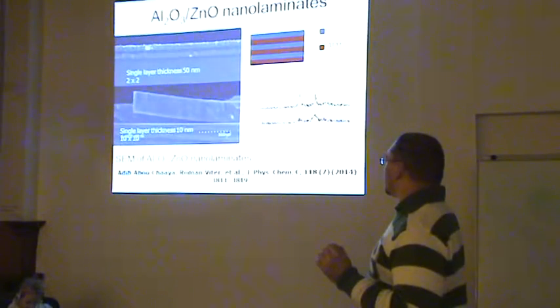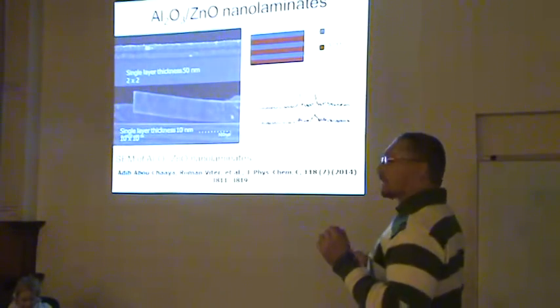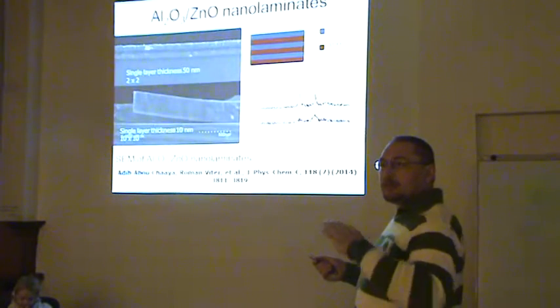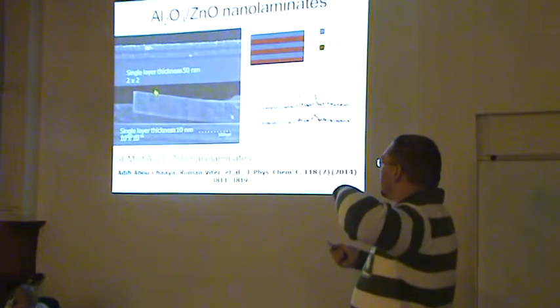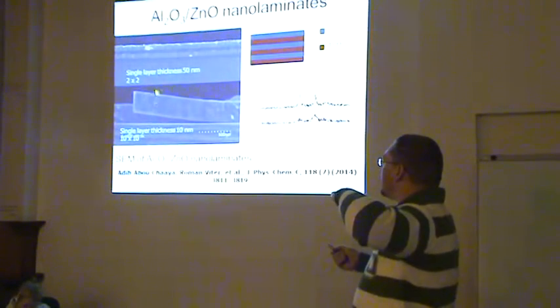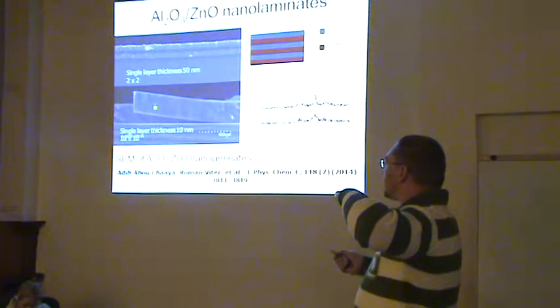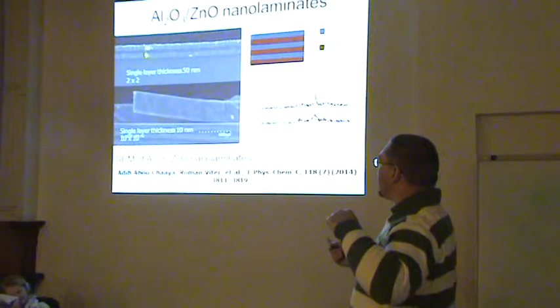And I will briefly show you our recent approaches. So here you can see SEM images, electron images of nanolaminates. It means that we deposited 2 different materials, layer by layer. The thickness of each layer is 10 nanometers. So 2 materials, aluminum trioxide is dark colored, and zinc oxide is white colored. So you see, first it was aluminum trioxide, then zinc oxide, then aluminum, then zinc.